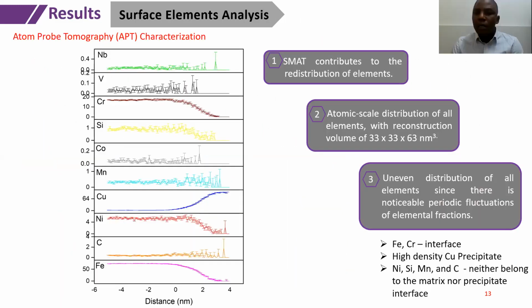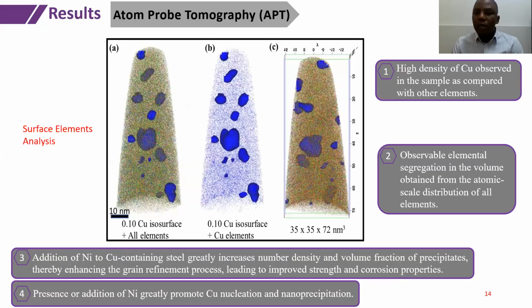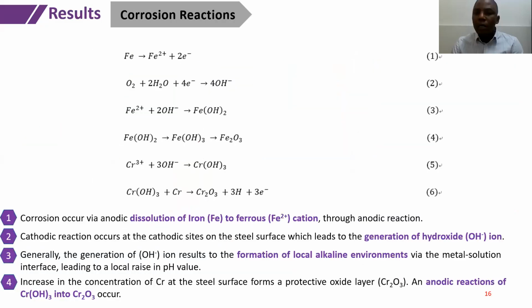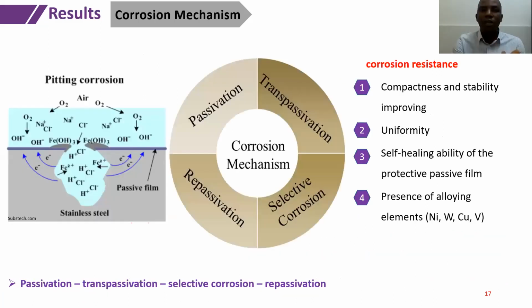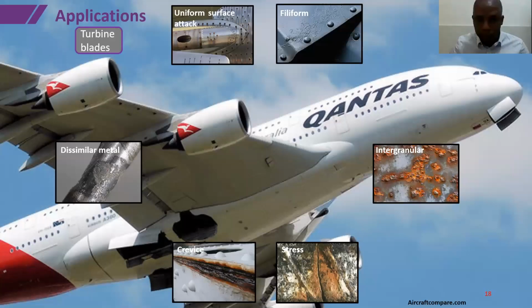And this is a summary of the APT that's also talking about the improved properties of the material. And this is also part of it. And the corrosion reaction shows that we start from dissolution of iron to iron 2+ ion and generation of hydroxide ion and formation of local alkaline environments, and all this contributes to the corrosion reaction. And in summary, this is the corrosion mechanism from passivation to transpassivation and passivation, and this actually prevents the pitting corrosion. And the major application is the fabrication of turbine blades.